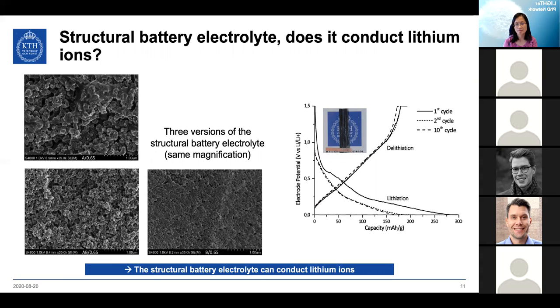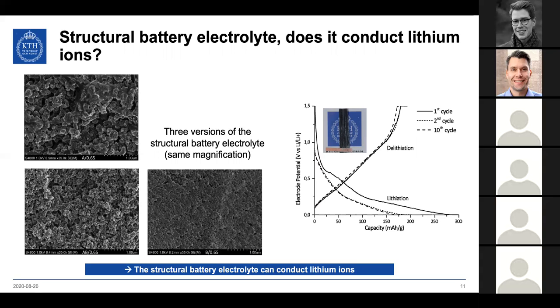Specifically, the x-axis shows the capacity of the carbon fibers in the structural battery electrolyte, which is not very far from that of pure graphite at 372 milliampere hours per gram. This shows that the structural battery electrolyte can conduct lithium ions. But what about carrying load?